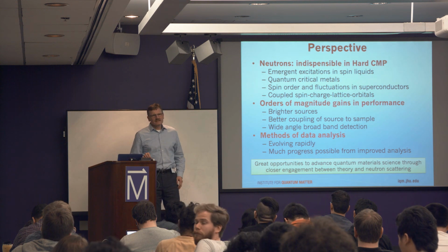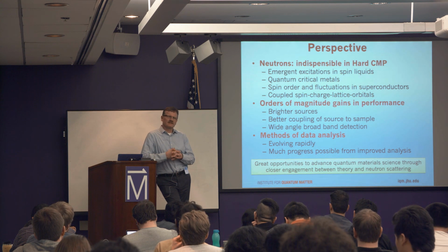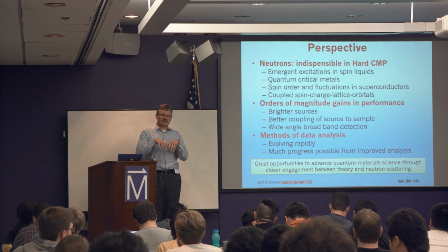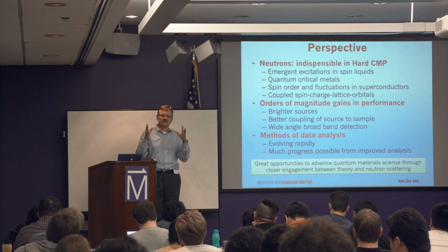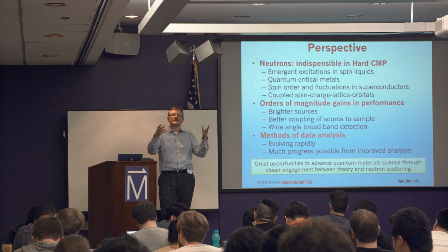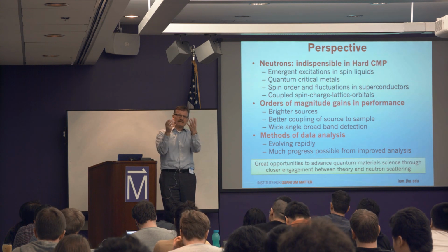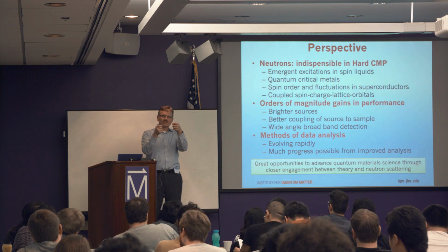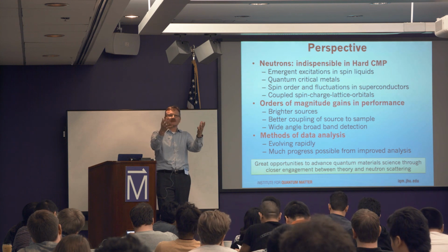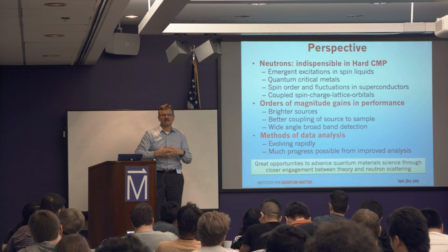Yeah, the answer is that there is a lot of very interesting physics in those systems. Actually, the Mirebeau group has been working on the dysprosium version of these and found something they call spin fragmentation, which is the coexistence of a short-range spin order with a long-range monopolar order. The idea is that the spin breaks into monopoles, and they actually order on the lattice. But this order then coexists with a disordered spin configuration, and the data is quite convincing, actually.